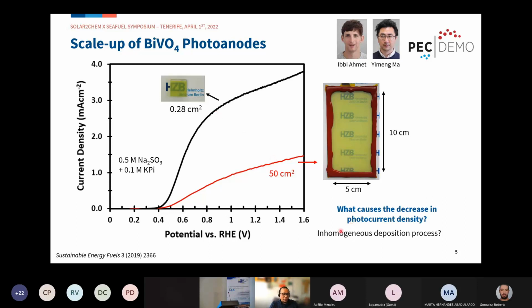One initial thought is that this inhomogeneous deposition process—we prepared this with spray pyrolysis, but scaling up our process from small to large scale may introduce some inhomogeneity. To test that, we took two small pieces from the large sample, one from the center and one from the edge, and measured the photocurrent-voltage curves. It turns out that when you take them at a small area, they perform pretty well—the same as the small area equivalent. That means our deposition process is fine, and this loss comes from factors other than the bismuth vanadate.